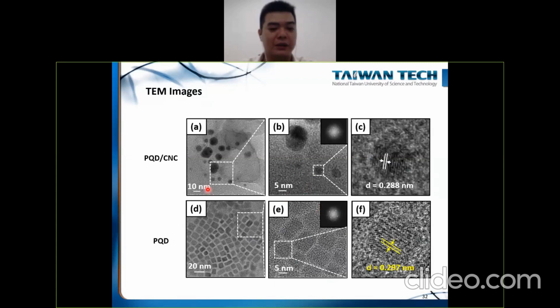But one possible problem is that upon the formation of the quantum dot, it may already be too large. So it is crucial to control the ratio of CNC and the PQD precursors to prevent forming these too large crystals with not as good light emission behavior.